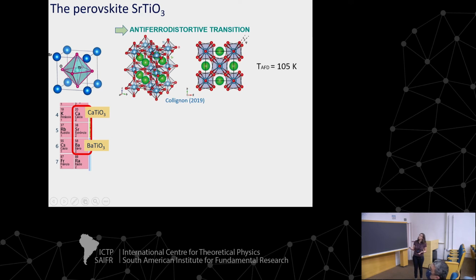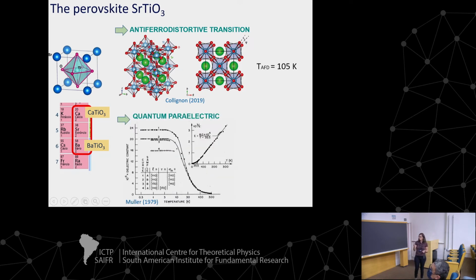So in terms of the structural phase transition, around 105 Kelvin we have the rotation of the octahedra. This is what we call the antiferrodistortive transition, which lowers the symmetry of STO. One of the characteristics known for a long time that is quite remarkable is the very high dielectric constant. So this is a material that is defined as a quantum paraelectric. It wants to be ferroelectric, but then epsilon saturates, never reaching the ferroelectric state.